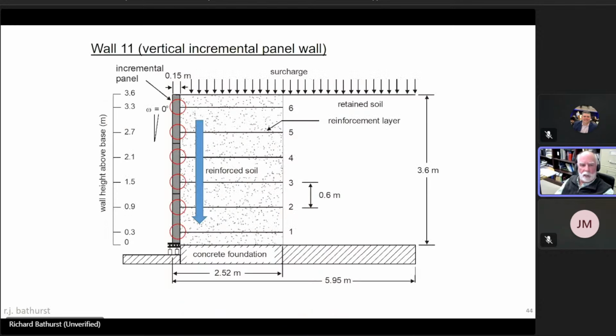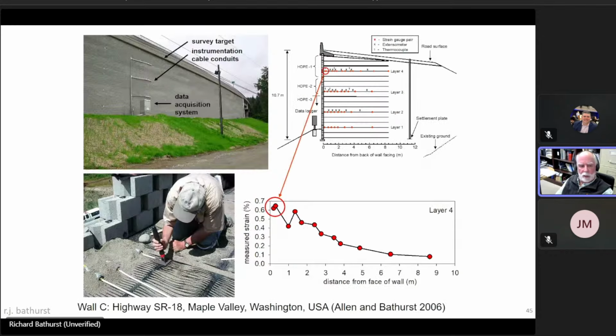Well, what is going on is that when this wall is being constructed, the soil is being placed and compacted, it moves downward relative to the facing, which is vertically rigid. There may be some additional vertical settlement of the fill as the wall moves out slightly. And what that does is it puts what I like to call parasitic loads on the connections, which are not predictable using force-based limit equilibrium methods of analysis. We saw this in our physical models under carefully controlled conditions, and we also saw this in full-scale field walls.